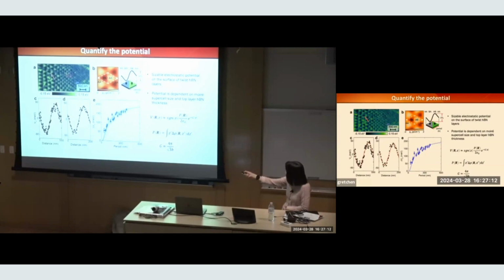If I'm looking at a supercell size of about 500 or 100, then my Z, when it changes from 5 nanometer to 7 nanometer, doesn't matter too much, okay? So we were able to measure the potential with pretty good accuracy. But this potential is really simple. It's a scalar potential. You can also create this potential by doing e-beam lithography.